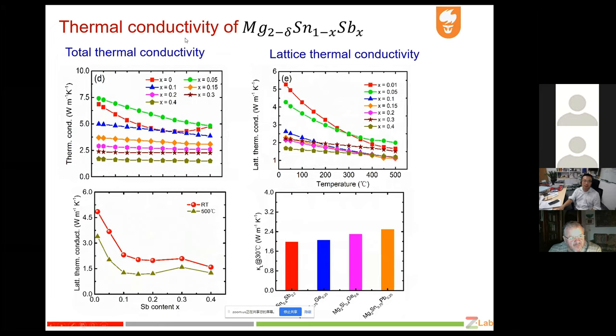Here is the thermal conductivity of this kind of material. We can see that with the increased doping of antimony, the lattice thermal conductivity is significantly reduced. Finally, the result is that this material's lattice thermal conductivity near room temperature is even lower than the reported magnesium tin alloy.